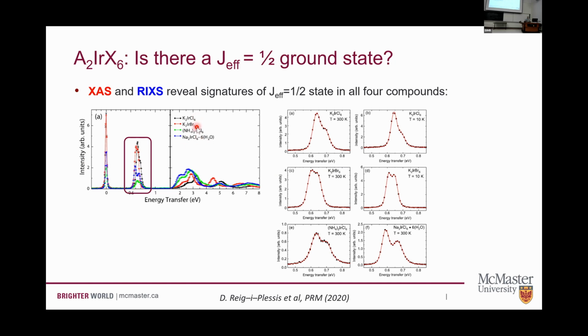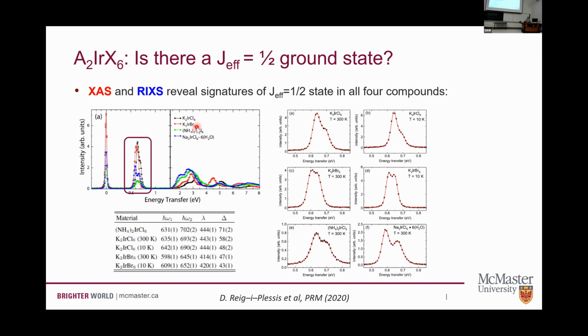And so when you move from these oxides into the halides, into these bromide and chloride materials, these are the best examples of this J effective 1/2 ground state that we've seen to date. Okay, so very small deviations away from this J effective 1/2 energy level scheme. And again, not nearly as sensitive to the local structural details as we might have expected ahead of time.